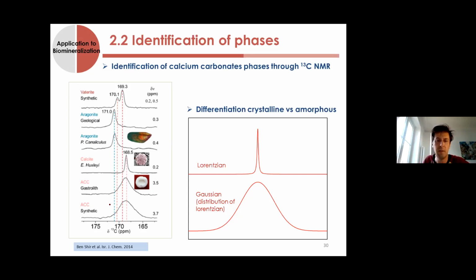And you can distinguish it on the basis of the line width, which is increasing in the case of an amorphous calcium carbonate, but also through the line shape itself, which is more or less Gaussian in the case of an amorphous sample, because it corresponds to a distribution of chemical shift, whereas the chemical shift itself is actually a Lorentzian line shape, which is very different in terms of shape from a Gaussian one. So that is something which is quite valuable in terms of information on the chemical environment.